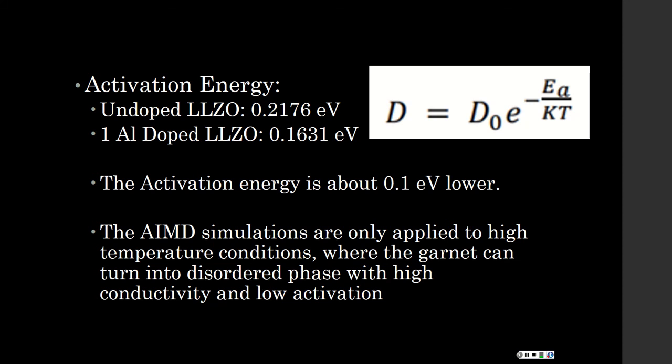There are a few reasons. We have considered so many standard structures, not experimental, and we have calculated the diffusivity at very high temperatures and then extrapolated it. That's not normal. In our experimental cases, those are run at room temperature. So that's the reason why our activation energy is lower than the experimental value.